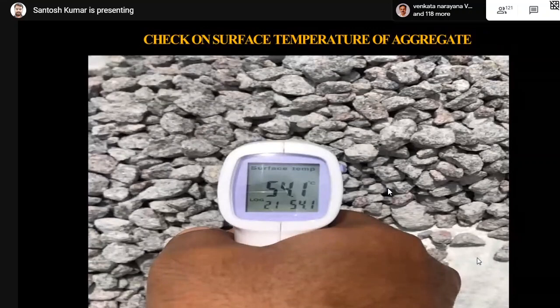When you take the case of the northern part of India, the aggregates are saturated and they are covered under cold climate. If the aggregates are below 15 degrees, your concrete may have a freeze and thaw effect. In those cases, you need to have air entraining admixture up to 5 to 6% based on the temperature of the aggregates and the temperature of the concrete. So different parts of our country have different scenarios. If you deal with hot areas, you need to add proper water absorption correction, and you have to store the aggregates properly. When it comes to cold climatic areas, you need to heat the aggregates so that a minimum of 15 degrees is attained in the concrete.